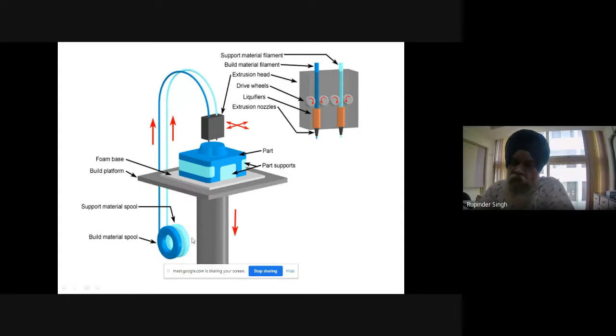I have a polymer material, a thermoplastic material, which is put in the form of a spool. This spool is fed into a liquefier chamber, right? From this spool, through the liquefier chamber, the material is deposited layer by layer. If you see a commercial printer, the diameter of this feedstock filament is normally 1.75 mm, the most commonly used size, but commercially these are available from 0.4 to 4.0 mm, right?